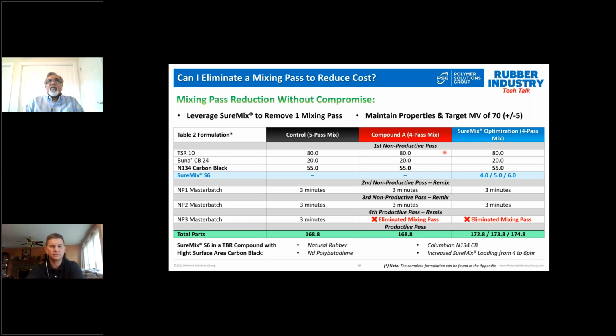So the customer was using an N234 or N200 series carbon black, and switched to an N134 to improve tread wear. Unfortunately, by doing so, they went from 4 to 5 passes. So the goal was to get them back to a 4-pass mix without compromising any of the properties such as modulus, tan delta, J double prime. This is a truck tire application. You must have guessed looking at the natural rubber and butadiene ratio as well as the type of carbon black used.